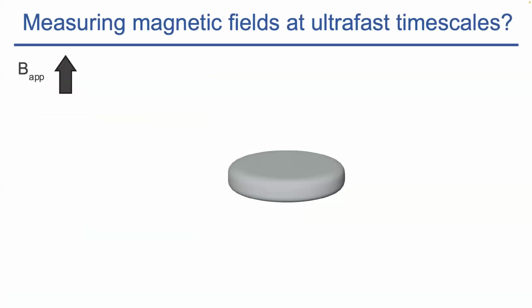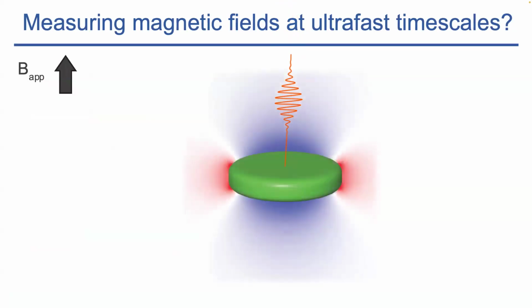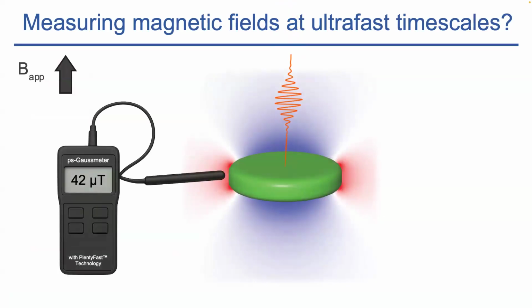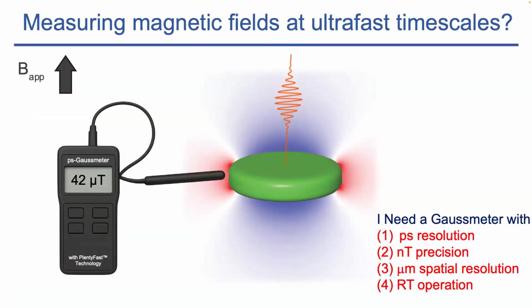So here's the experiment. You take the material in the normal state, you apply a small magnetic field below HC2, 10 millitesla or a few millitesla. You photoexcite the material, and then you look for expulsion of the magnetic field. So what you want is to use a Gauss meter that measures maybe either on the edge or immediately above to measure whether photoexcitation expels the magnetic field. The only problem is that your Gauss meter needs picosecond resolution, nanotesla precision, micrometer spatial resolution, and most importantly, room temperature operation.